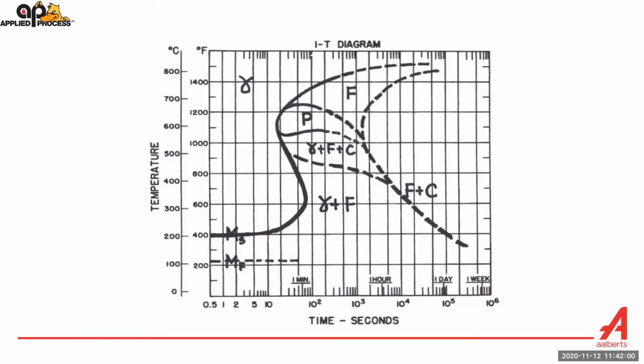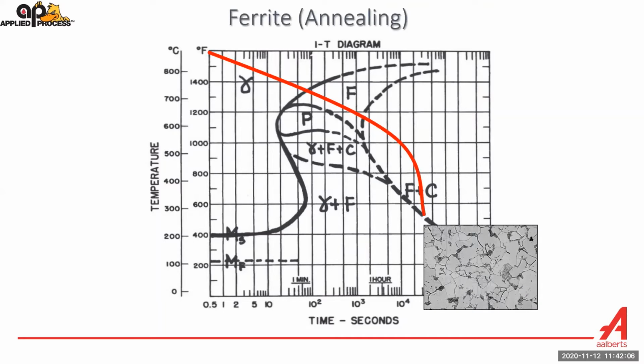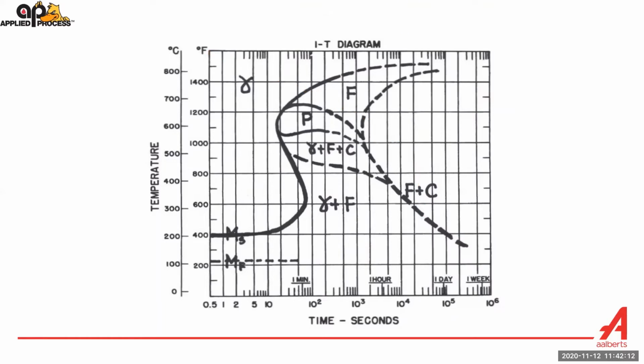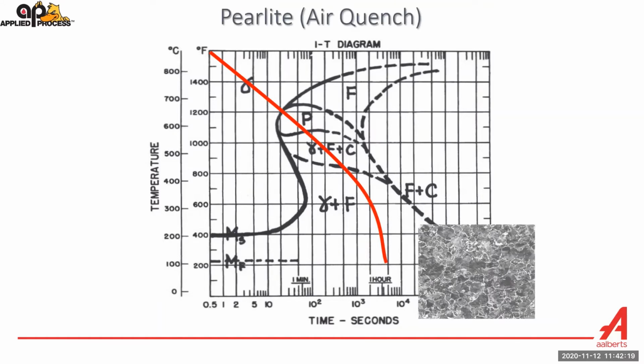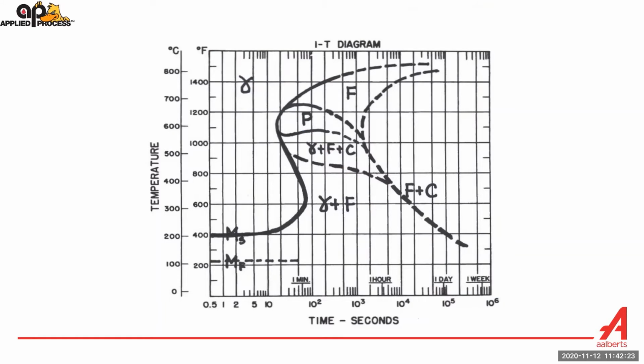If we start with steel at about 1600 degrees Fahrenheit and we slow cool it, you get a ferritic structure, and that would also be called annealing. So that's a heat treatment process many people are familiar with. You could cool faster by perhaps using fans and air cooling, and you get a pearlitic structure. Very common processes are quench and temper.